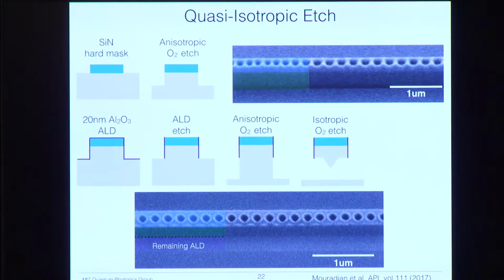And then this is the part that allows us to get the suspended beams. We do this isotropic etch, or quasi-isotropic, because it does have a directionality depending on the facet of the diamond. And so, as I said before, this direction etches much faster than this direction. So we get these funny triangle-shaped structures, but if we etch enough, the triangle will etch away faster than this bottom surface here. So in the end, we'll get a rectangular cross-section. And so this is a scanning electron micrograph at this stage, where you can see the sheath of the remaining ALD. This here is diamond with ALD on top, and then the remains of our silicon nitride mask.